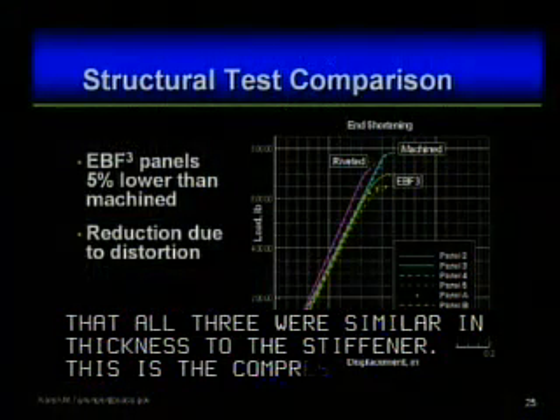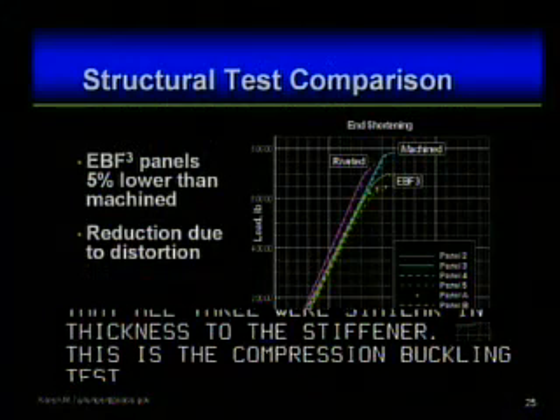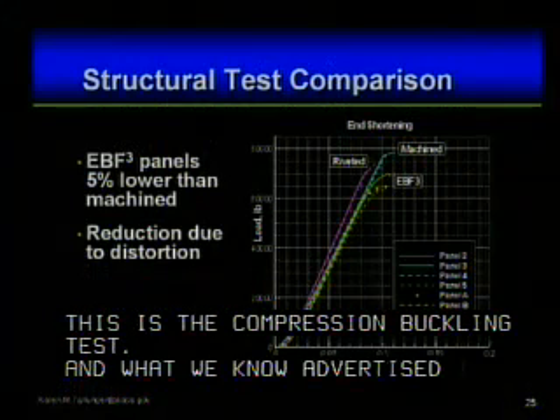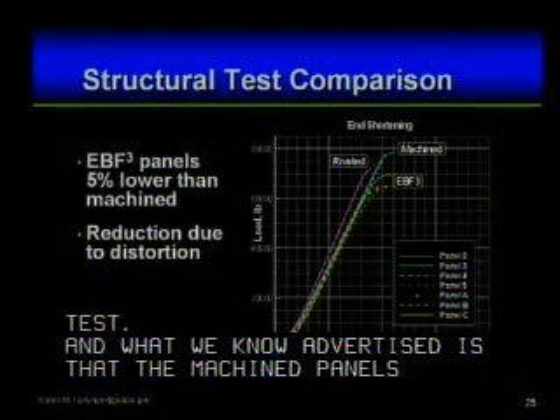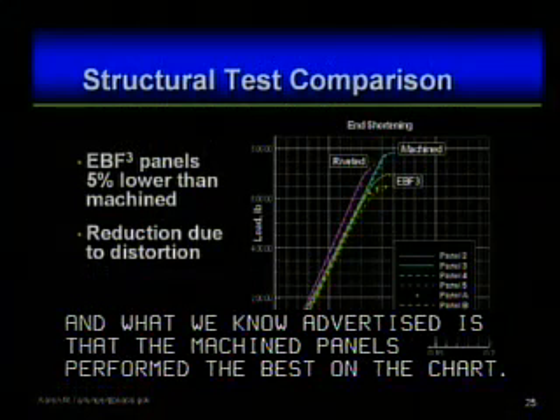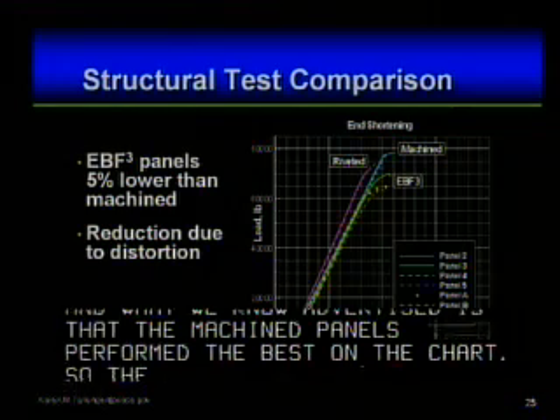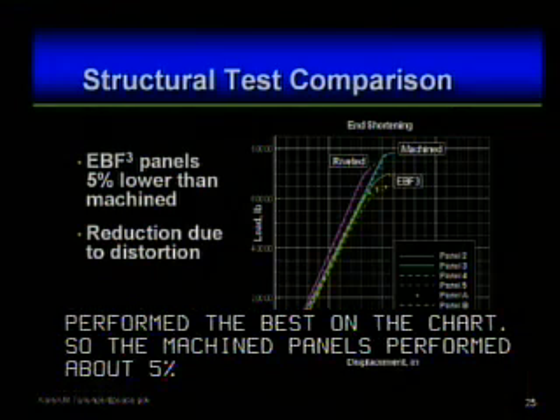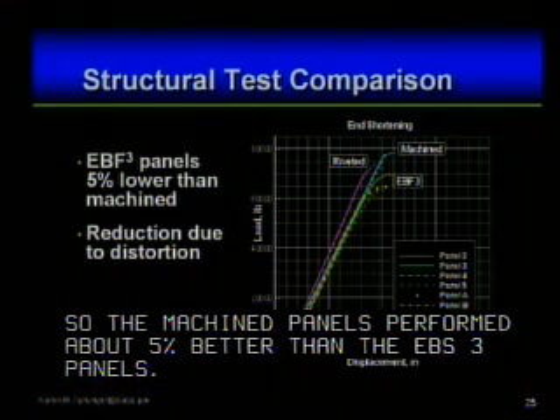What we noticed is that the machined panels performed the best. On the chart, you see load on the vertical axis versus displacement. The machined panels performed about 5% better than the EBF3 panels. The riveted panels are a little bit stiffer because of that extra material, but the riveted and the EBF3 panels gave us comparable max load capacity. One of the things that we've noticed in the EBF3, and I'll talk about it a bit later, is that we do have some distortion that occurs because of the focused heat source.